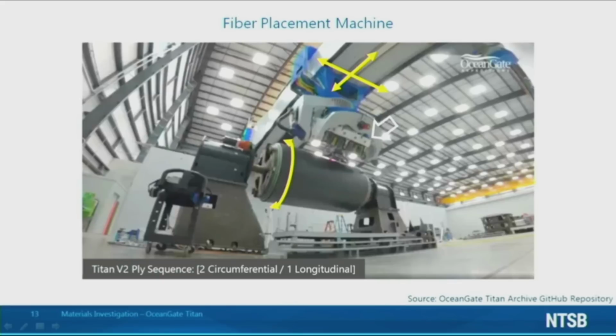The head can apply multiple tapes in multiple directions. For the first two plies, the tapes were applied in the circumferential direction, like a spiral from one end of the hull to the other. For the third ply, the tapes were applied in the longitudinal direction. The sequence was then repeated until 133 plies, approximately 1 inch of pre-preg material, had been applied to the hull. The hull then proceeded to curing and co-bonding.